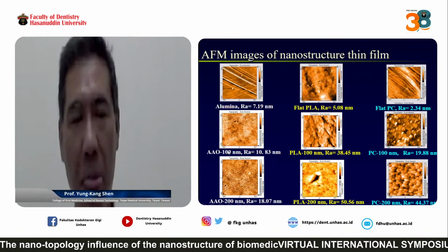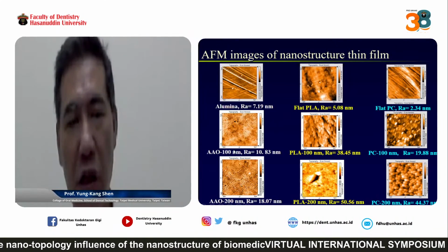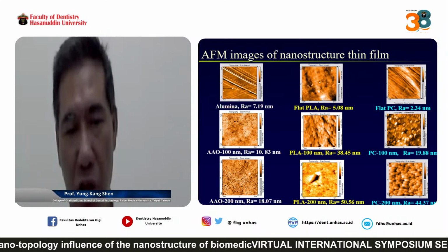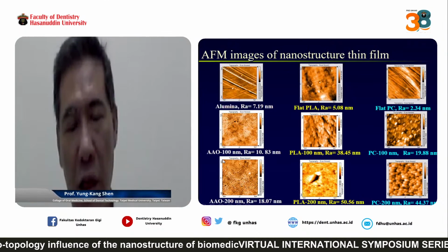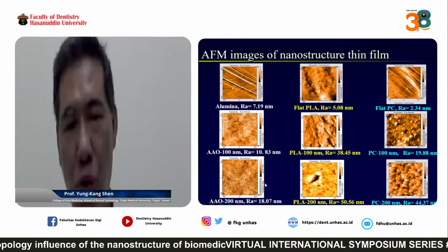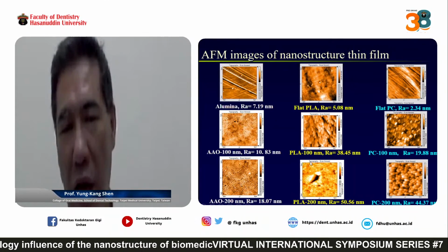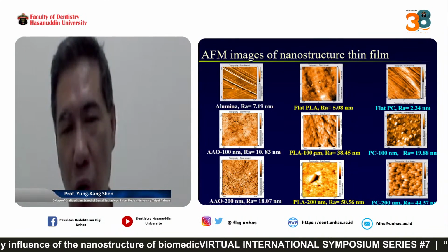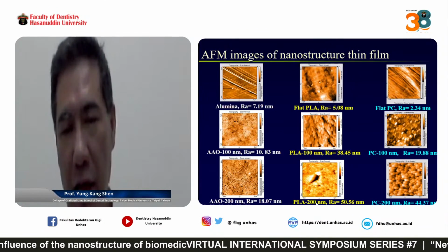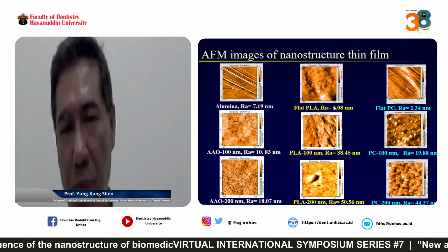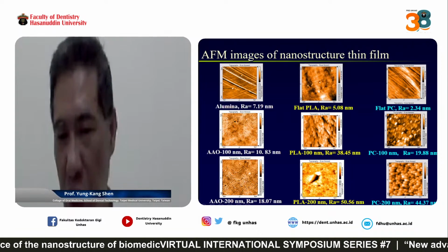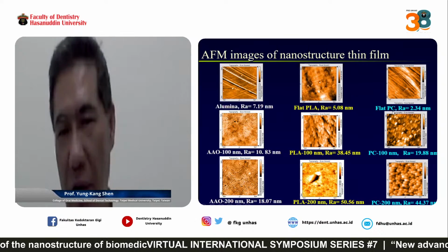After you get the AAO with the nano hole, you can see the surface roughness increase. And for the larger diameter, the surface roughness is also larger. You can see PLA 100 nanometer and PLA 200 nanometer. Compared to the flat PLA, the surface roughness increases. It is also the same result for the PC.